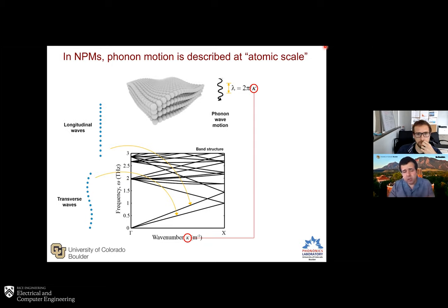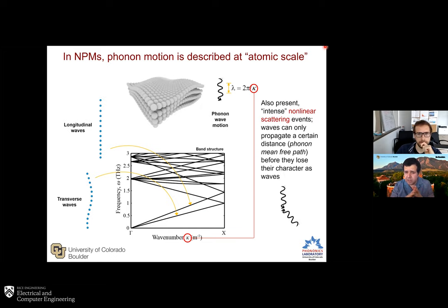However, it's important to note that that wave picture, which is actually a linear harmonic picture, is only an idealization. It's useful because it allows us to understand basic underlying characteristics of how phonons propagate in that medium. But as I was saying earlier, scattering is still very important. And in this case, I'm talking specifically about phonon-phonon scattering. So that's also a part of that problem. So there's really no such thing as a linear version of this problem.